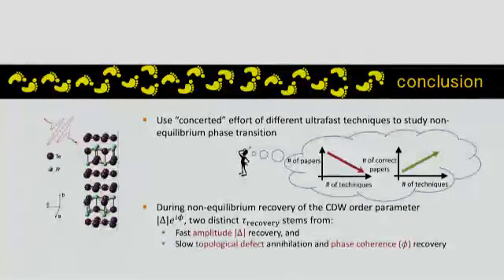Should the domain wall propagation and annihilation be affected by temperature? Like the rate at which they move around and merge? Yes, it should depend on temperature. Have you checked whether that's temperature dependent? Not yet. All the experiments are done at room temperature. These experiments are all done at room temperature? Yeah, all except for ARPES, where the data is taken at the lowest temperature.